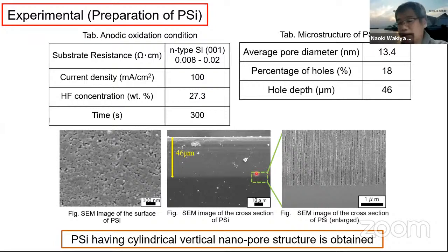And this is the experimental part, the preparation of porous silicon. The porous silicon is synthesized by anodic oxidation using these conditions. And we use a highly doped N-type silicon substrate. As a result, this is a SEM image of the surface of the porous silicon. The oxidation time is 300 seconds. It is only 5 minutes. But using this anodic oxidation, the 46 micrometer porous silicon layer is obtained.